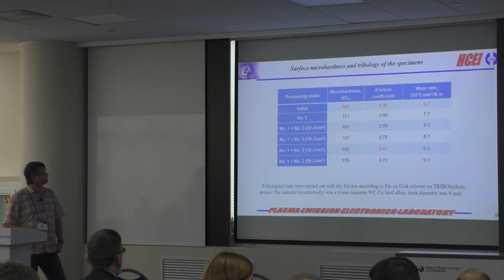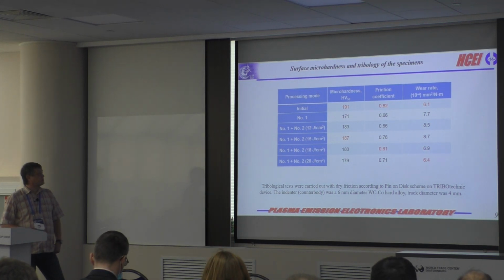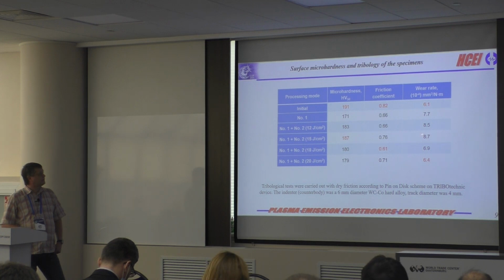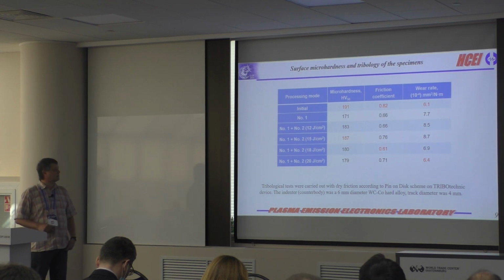Also, surface microhardness did not change in all modes of treatment. Friction coefficient after treatment by pulsed electron beam decreases in all modes, and wear rate in one mode, the last mode, is close to the initial value for the initial sample.